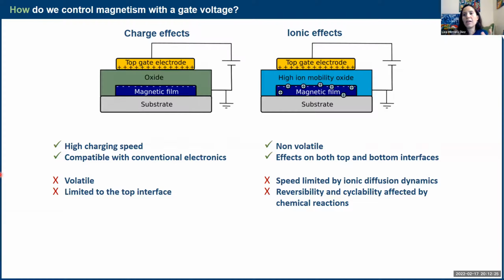On the other hand, it has a few downsides, if you like to call them downsides. It's volatile, which means that it's a charge accumulation. If you get rid of the applied voltage, then the charges go away, and you go back to your initial state. And it is also limited to the top interface. We're talking about a charge accumulation in a metal, so this is really concentrated at the top surface. So you also need your magnetic material to be a nanostructure.